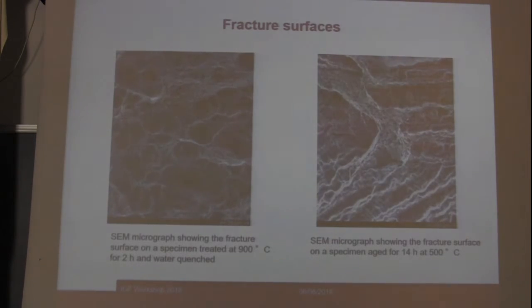More information could be obtained by looking at the fracture surfaces of the tensile specimens. On the left, we have the fracture surface morphology of the alloy after solution treatment at 900 degrees centigrade, and you can see the surface is characterized by dimples. On the right, you can see the fracture surface after aging for 14 hours. In that case, we have a mixed mode mechanism, with areas characterized by dimples and areas characterized by brittle interdendritic fracture.